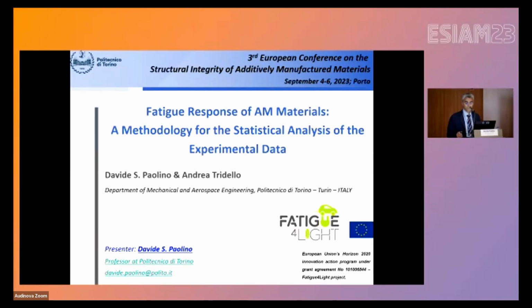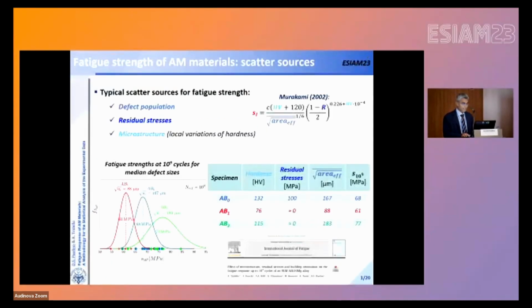The talk is devoted to the fatigue response of AM materials, in particular to a methodology for the statistical analysis of the experimental data sets that, especially in case of AM materials, are strongly, largely affected by the scatter. And indeed, there are several scatter sources in fatigue, and the most relevant ones are taken into account also in the well-known Murakami formulations for the